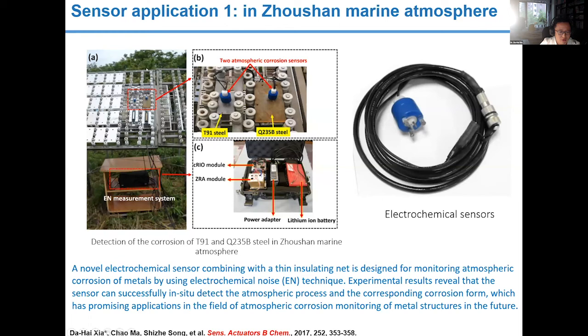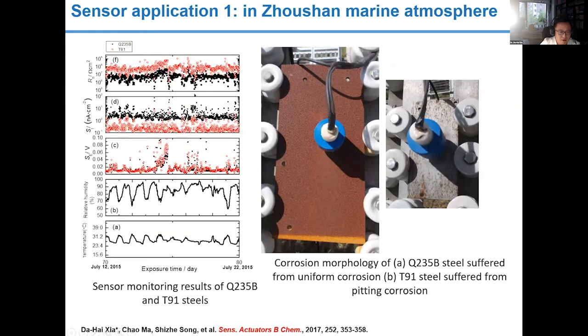The noise resistance of Q steel is 10 times lower than that of the T steel. So it means that the corrosion rate is very high.